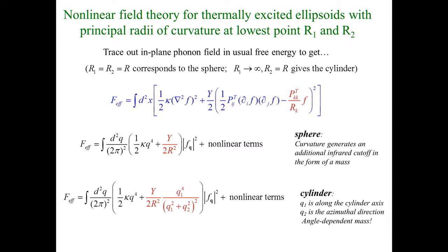And if we take the spherical limit, where the R's are equal, what happens? Well, this 1/2 kappa q to the 4th acquires a mass. The Gaussian curvature generates a kind of mass that's proportional to the Young's modulus and inversely proportional to the radius squared. And that changes the physics. And you can think of a sphere, if you look at the outward displacements of a sphere, that's what F is representing here. It's going to feel the stretching restoring force associated with the Young's modulus because it's a sphere. Whereas a sheet of paper, if I just change F, it's translationally invariant, nothing's going to happen.